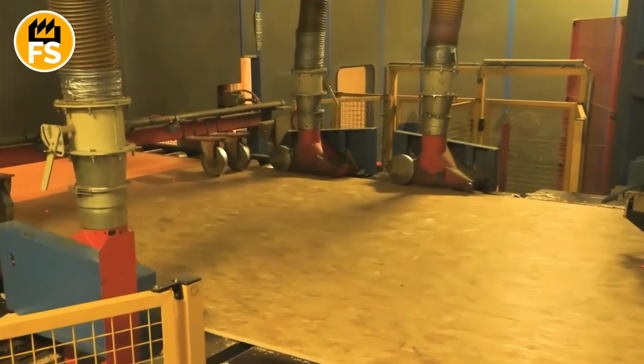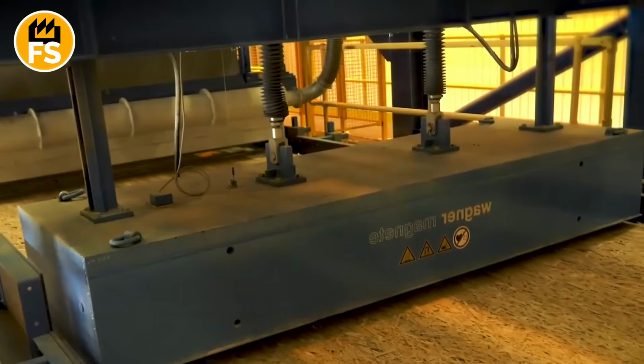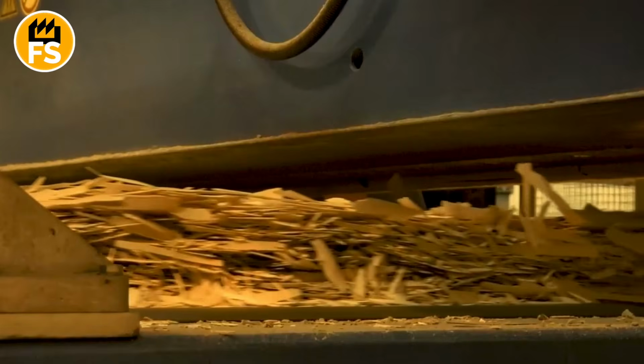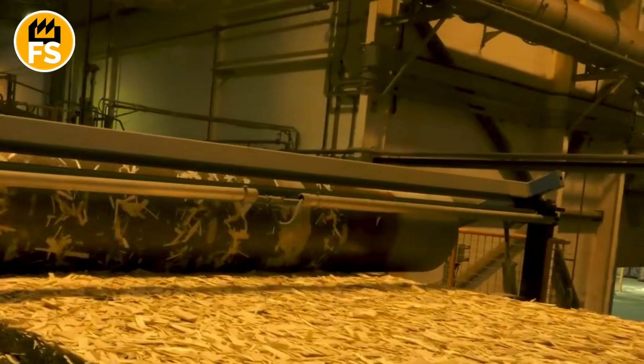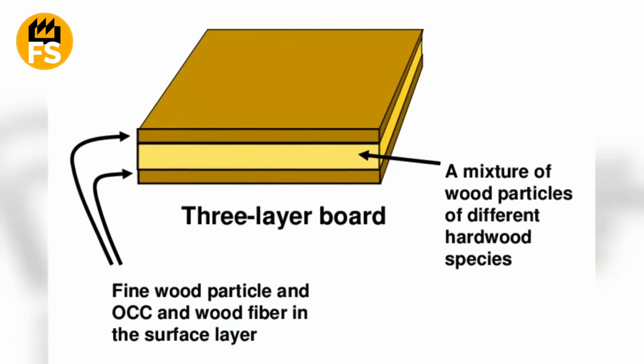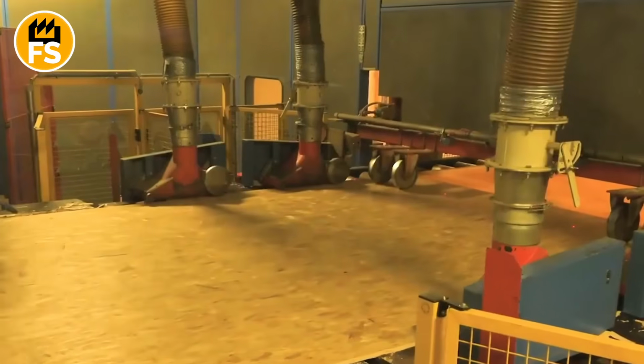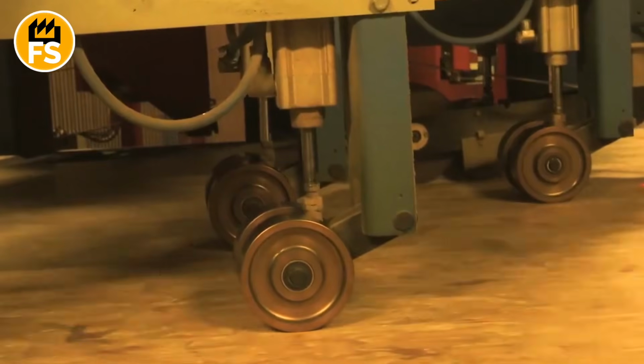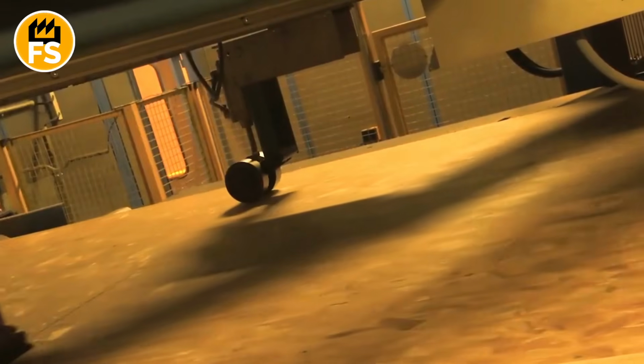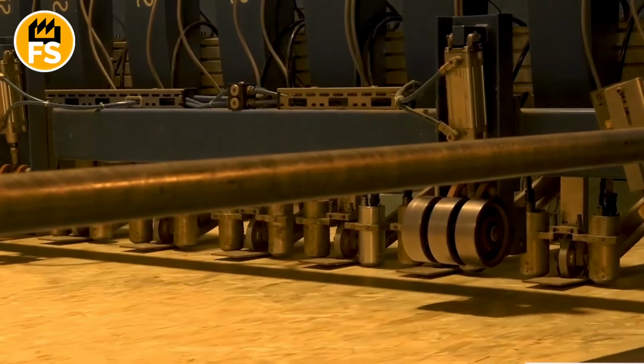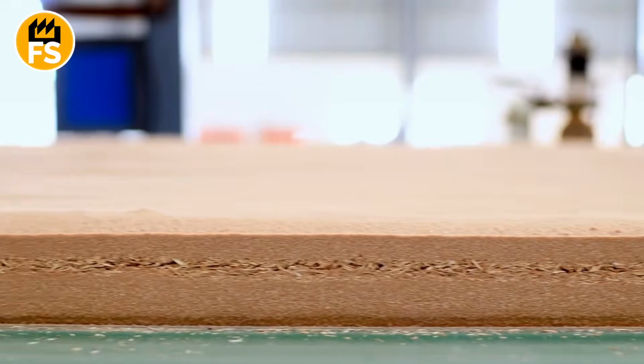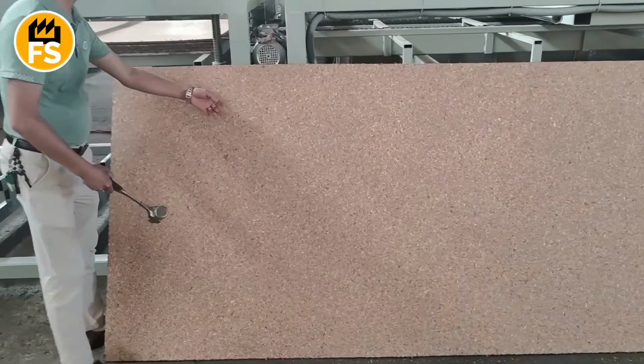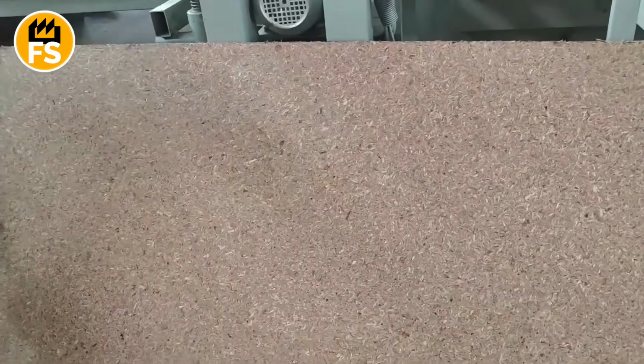First, the bottom layer is formed. The choreographers lay out the strands so that they all lie parallel to the long edge of the future panel, that is, lengthwise. Then comes the turn of the middle layer. Here the strands are laid out perpendicularly, that is, crosswise. And finally, the top layer is again laid out lengthwise. As a result, we get a thick, fluffy, 3-layer pie, where the fibers in each layer are perpendicular to the fibers in the adjacent one. It is this cross structure, which imitates the strength of plywood, that is the secret that makes oriented strand board incredibly strong in bending and resistant to deformation.